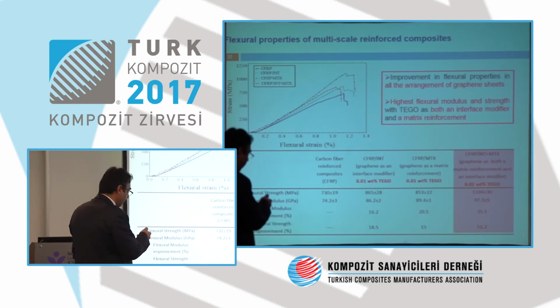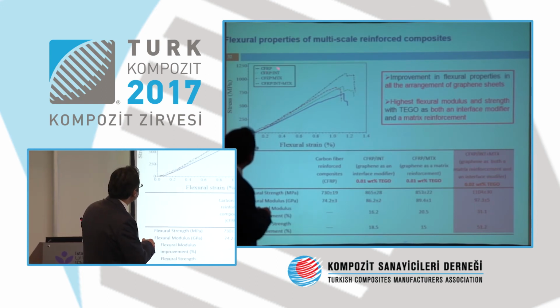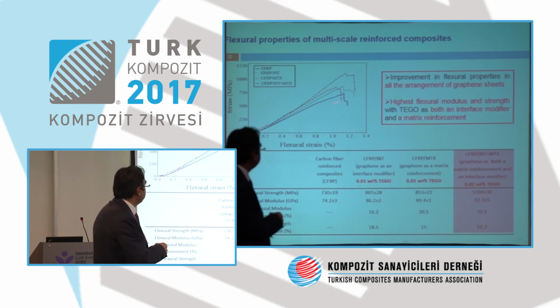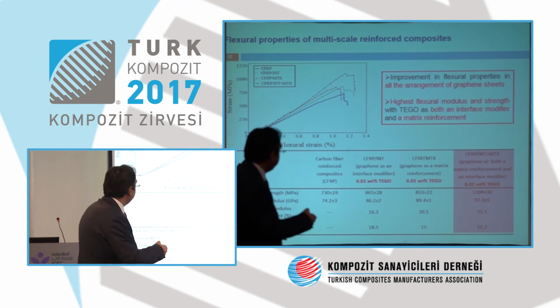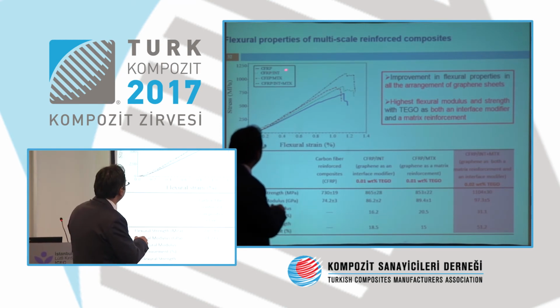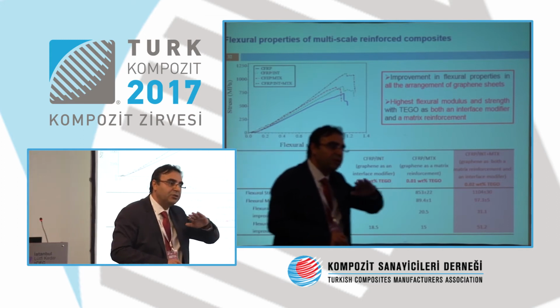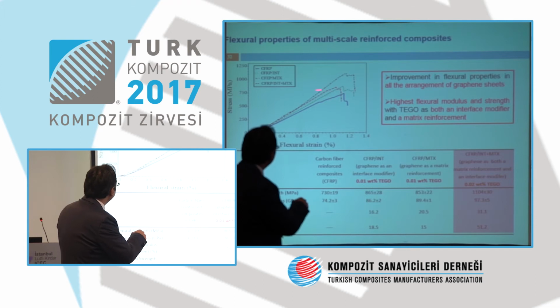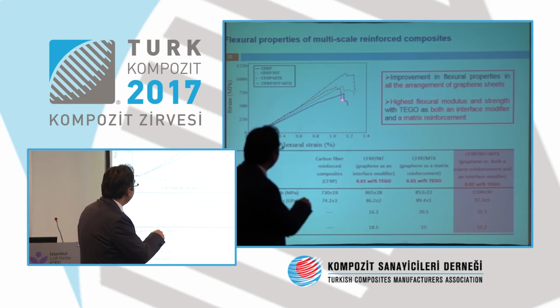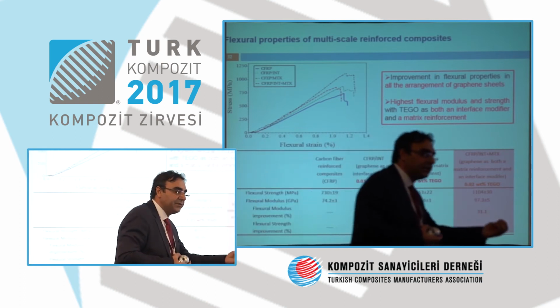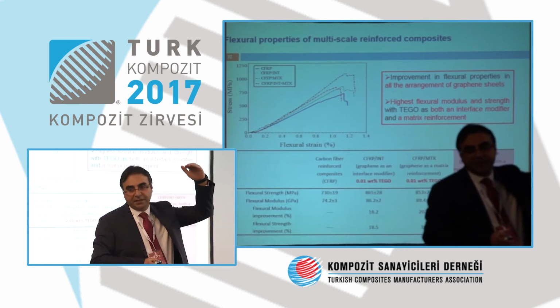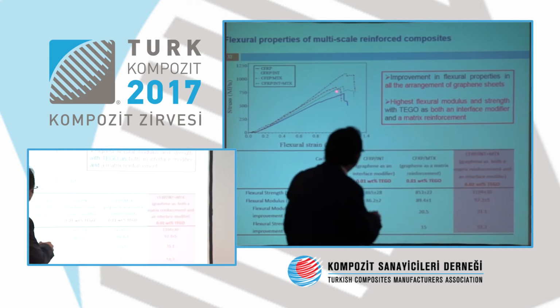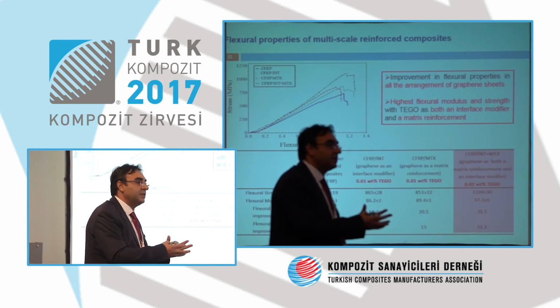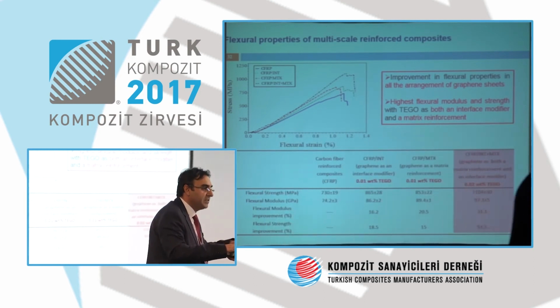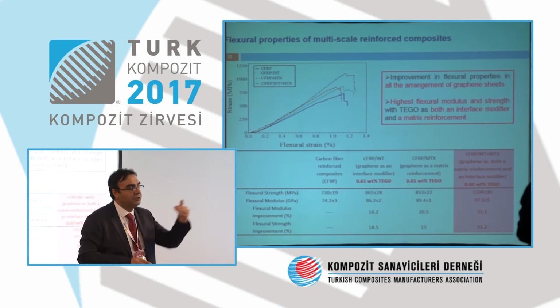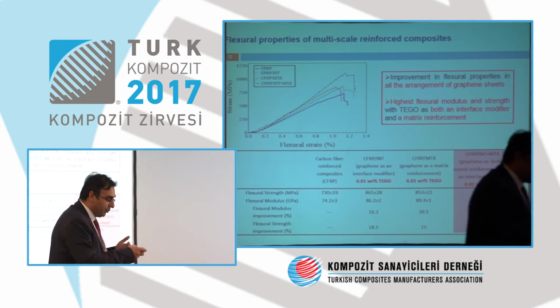And we look at flexural strength. If you look here, this is CFRP, carbon fiber reinforced plastic, in a solo manner, which is the neat one. And then if you add a certain amount of graphene to the interface, meaning only to the textile, this is the improvement we have. And then if you add to the matrix, the red one, but if you reinforce both the interface and the matrix, the improvement is significant. You see that when a composite system needs to be reinforced, it is not enough to reinforce only the interface; you have to reinforce the matrix so that there will be a continuous force transfer. Otherwise, you will not be able to see the improvement at all.